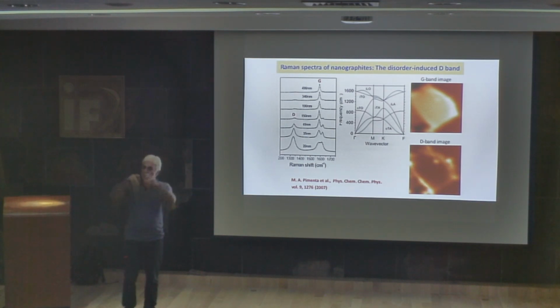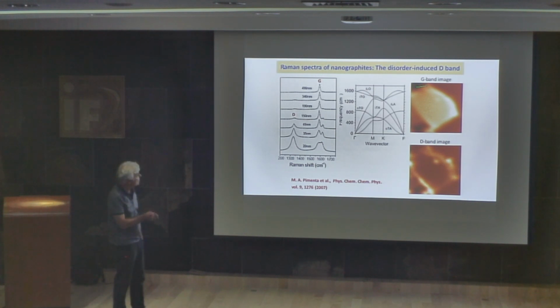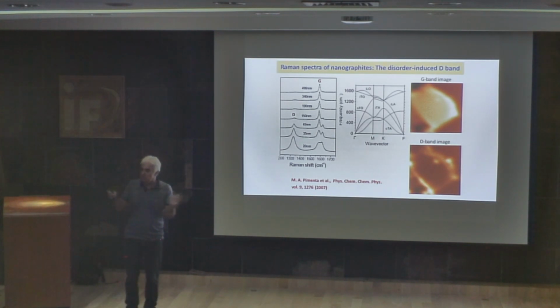And those bands appear only when we have defects. For example, this is the Raman image of the G band. Raman image means that this is a piece of graphite, okay? Then I'm collecting only the light that comes from this peak. I put one filter and I collect only the light that comes from the G peak. Then I have the G band image. But I can also probe only the light that comes from this part here, which is the image of the D band. And you can see that in the center of the sample, since there are no defects or no disorder, I don't see the signal of the D band, but near the borders or when we have defects, the D band appears. So to see the D band, we need to have defects.